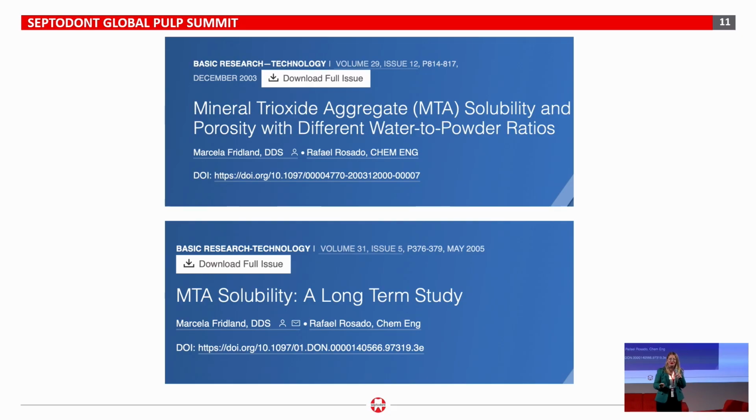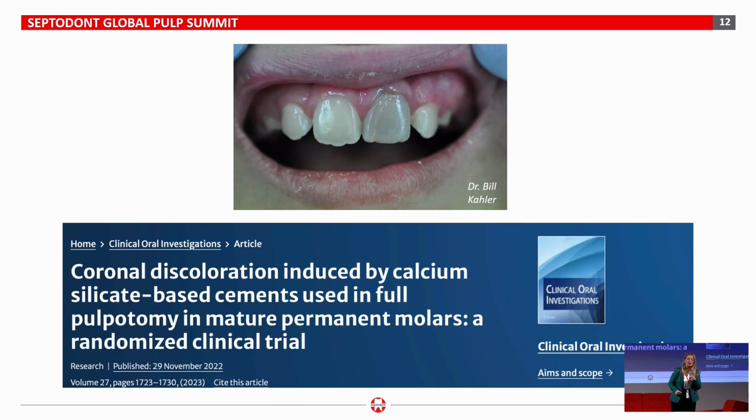Stop doing it. Do not open sachets, leave them open and reuse them. Gilles Richard mentioned a very, very important property. It's hygroscopic. It collects the moisture from the environment. So two very, very bad practices are opening sachets and adding as much water as you like. Bismuth oxide causes tooth discoloration.